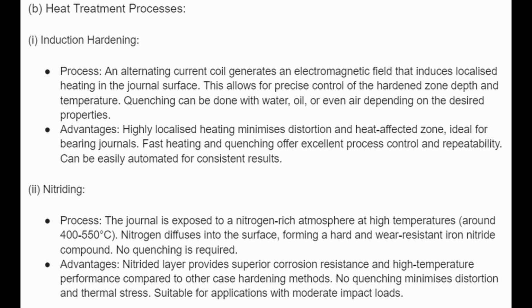2. Nitriding. The process: the journal is exposed to a nitrogen-rich atmosphere at high temperatures, around 400 to 550 degrees C. Nitrogen diffuses into the surface, forming a hard and wear-resistant iron nitride compound. No quenching is required. The advantages: the nitrided layer provides superior corrosion resistance and high temperature performance compared to other case hardening methods. No quenching minimizes distortion and thermal stress. It's suitable for applications with moderate impact loads.